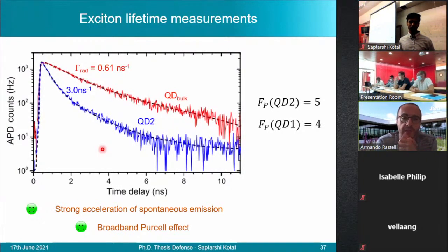Do you have independent measurements of the lifetime taken under some resonant conditions? I'm not sure what you're asking me. Essentially the argument you are giving is that you see a sharp rise. If you had a slow relaxation, you're exciting in the wetting layer, and these carriers need to relax inside the quantum dot and populate the exciton. So you're saying essentially if this relaxation would take long, I would expect a slow rise. Is this the argument? Yes, precisely. Okay. So not only a slow decay, but also a slow rise. Probably yes.